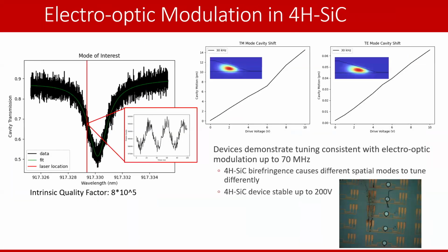But nevertheless, we're still able to measure the electro-optic shift of these cavities by applying an AC field. Interestingly enough, there's a DC screening effect from the metal contacts being Schottky contacts to the silicon carbide. So you don't see electro-optic shift when you apply a static voltage, but you will when you apply an AC voltage. And so we saw electro-optic shift of the cavities up to 70 megahertz. And this is actually limited by our cryostat wiring, not by the device itself.